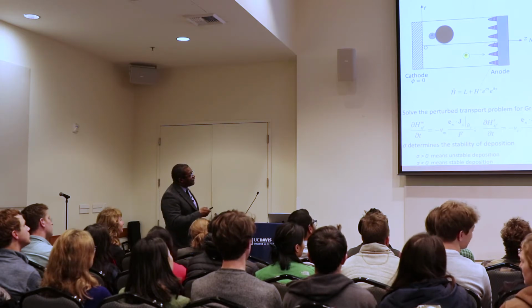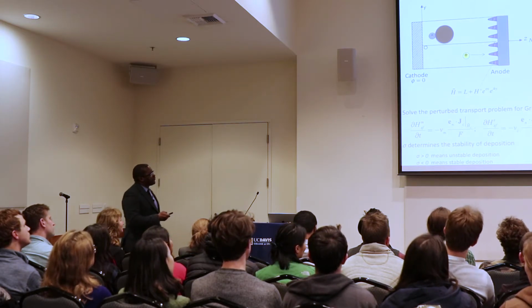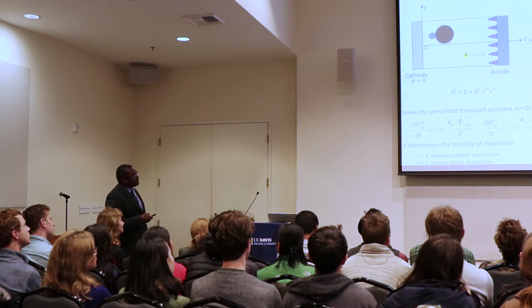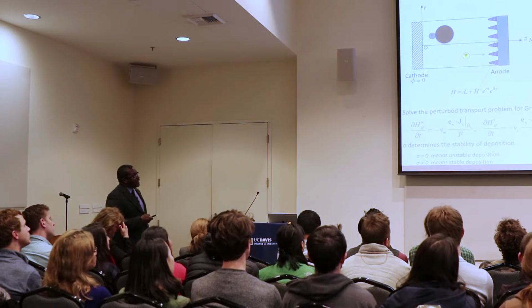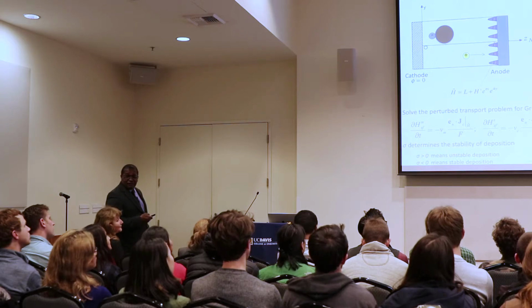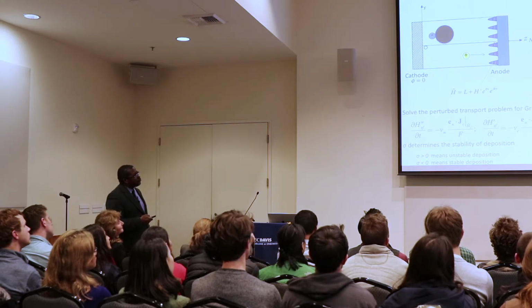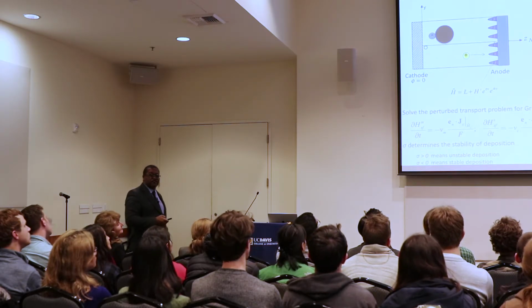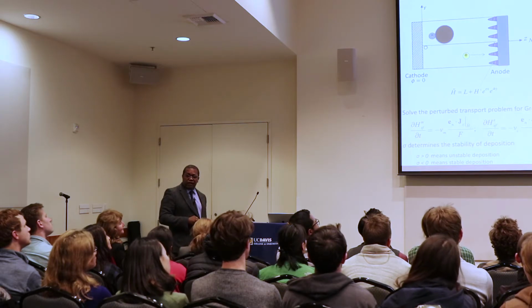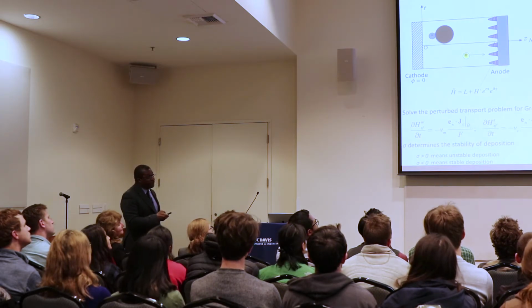So this is the conservation of mass. This equation basically is a flux balance that says that we have diffusion, we have migration under an electric potential, and the new term we added to this thing is pressure-induced diffusion. So everything in this equation is known but for this new term.